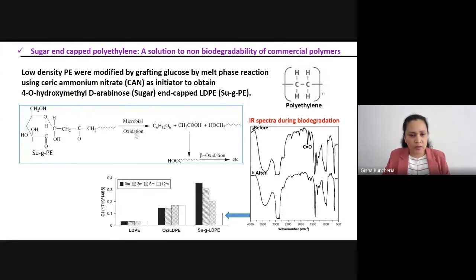During the microbial oxidation, microbes consume the sugar and slowly start the oxidation at the chain end. Now the carbonyl group is oxidized to carboxylic acid, leaving behind a hydroxyl terminated polyethylene. This polyethylene further degrades through the beta oxidation process. It is reported in the literature that in normal circumstances, polyethylene degradation takes hundreds of years. But by this method, we created some active sites for the microbial oxidation. So the degradation process of polyethylene initiates at early stages.